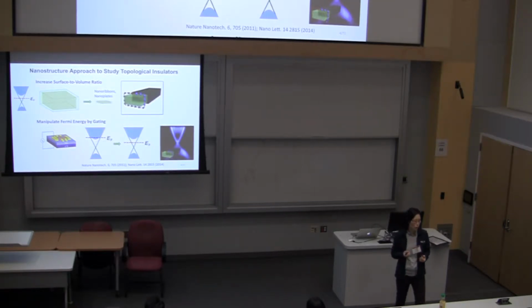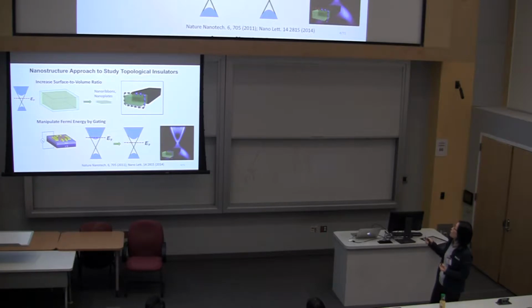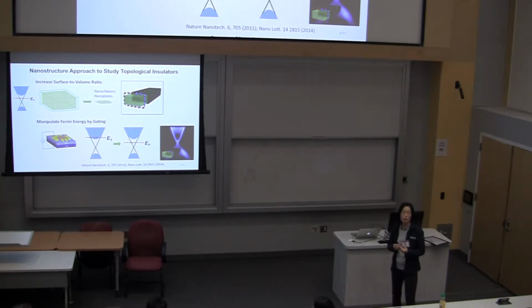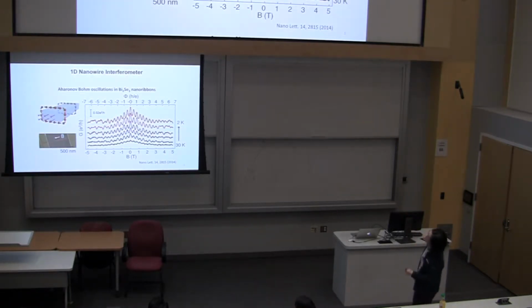So here is a phase-sensitive measurement you can do in nanostructures, where the interferometry setup comes for free by virtue of the fact that your system is already at the nanoscale, where the electrons will start to interfere with each other. So if you take care of your materials very well, you will see this. So this is bismuth selenide nanoribbons. This is grown by, I would say, metal catalyzed chemical vapor deposition.